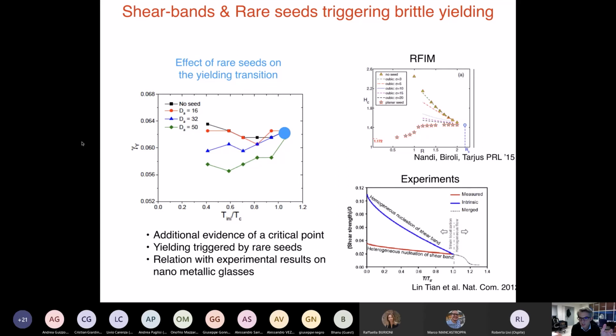So when you go from hundreds of nanometers to a bulk value, it's the same effect. When the system is hundreds of nanometers small, it means that in principle you cannot have a big seed inside the system. Instead, when you have a very big system, you can have a big seed inside. So you expect to see a very different value of gamma y in a very small system compared to a very large system.